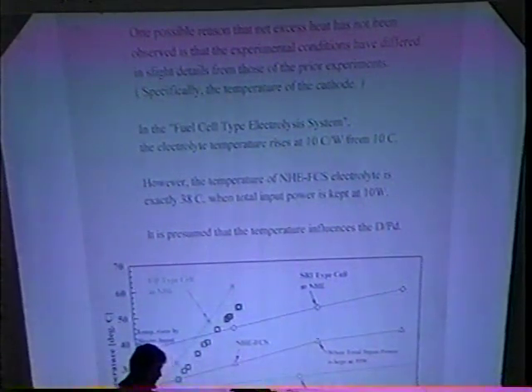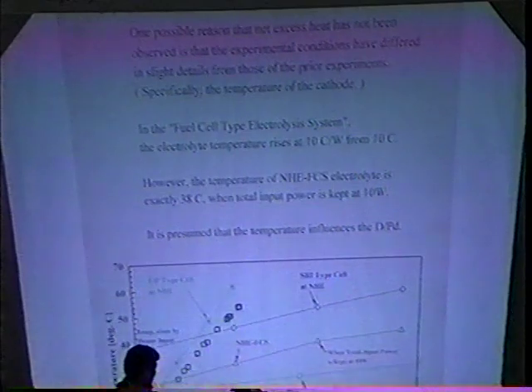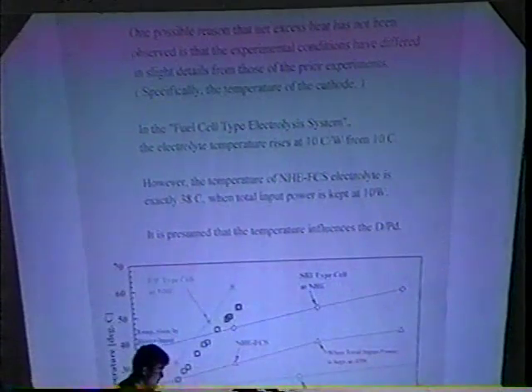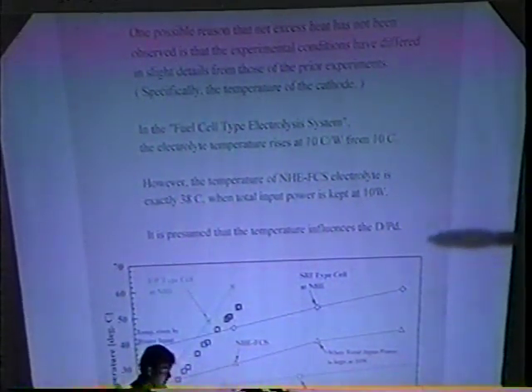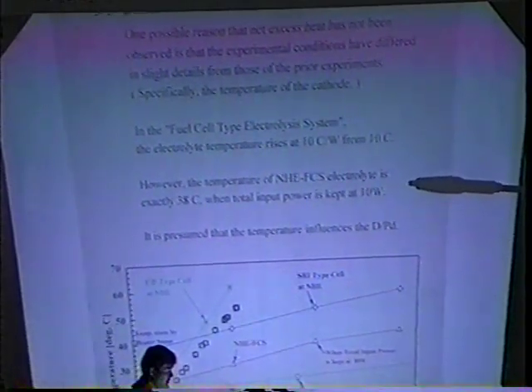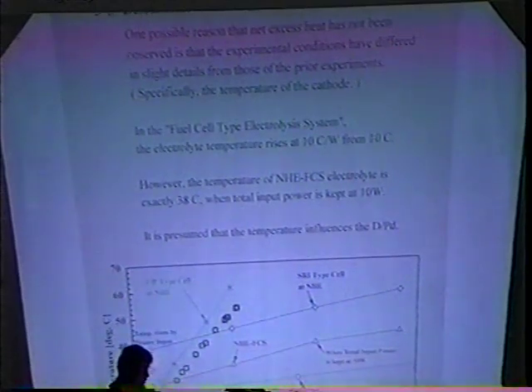One possible reason that net excess heat has not been observed is that the experimental conditions differed in slight details from those of the prior experiments, specifically the temperature of the cathode. This figure shows the electrolyte temperature versus input power for several experimental cells. The black square is from the fuel cell type electrolysis system, and the red triangle is from NHE-FCS. In the fuel cell type electrolysis system, the electrolyte temperature rises at 10 degrees C per watt from 10 degrees C. However, the temperature of the NHE-FCS electrolyte is exactly 38 degrees C when total input power is kept at 10 watt. It is presumed that the temperature influences the D by PD.